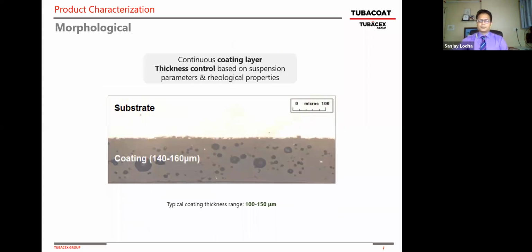So this coating is a continuous homogeneous layer managed through an automated process, as I said, and through rheological suspension properties. In the automatic control process, this coating is 150 micron, 0.15 millimeter, and we're able to control the thickness across the length of the pipe with the same thickness, where we measure at the start, at the middle, and at the end, and we get minimum, maximum, and average thickness properties, and we're able to control the thickness in a very unique way. Next slide, please.